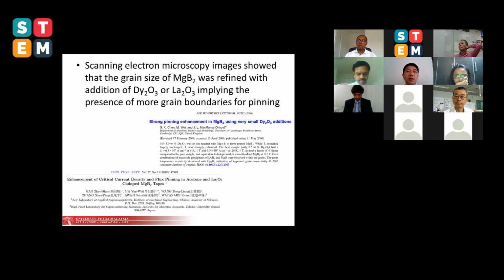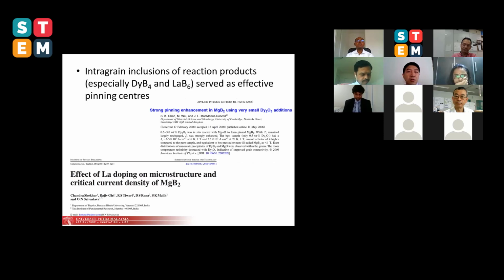The second reason is that we also noticed, as reported previously, the grain size of MgB2 was refined by addition of either dysprosium or lanthanum oxide. If the grain size is reduced, that also implies that you have more grain boundary for pinning. And the third reason is that if we make use of the two dopants for reaction with Mg and B, you have byproducts or impurities that form, and in turn, those impurities can act as effective pinning centers.